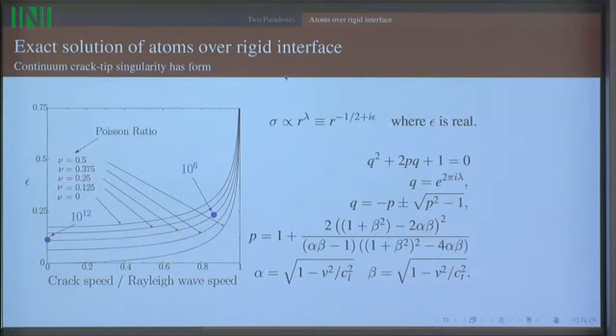atomic rows high a system would have to be in order for you to have to worry about a stress going through a complete cycle, or a displacement going through a complete cycle, so that the lower solid would penetrate the upper one within an estimated atomic distance. So if your system is 10 to the 6 units high, then you should just guess from continuum theory that you'd be facing interpenetrating surfaces here. If it's 10 to the 12 atoms high, you'd guess you might be facing interpenetrating surfaces, and so on. So I wanted to see if it was possible to resolve that, if solutions could actually exist with this oscillating character at the front. Maybe if you pose the question in a discrete case rather than a continuum case, the math would figure itself out and allow things like this to come into existence.